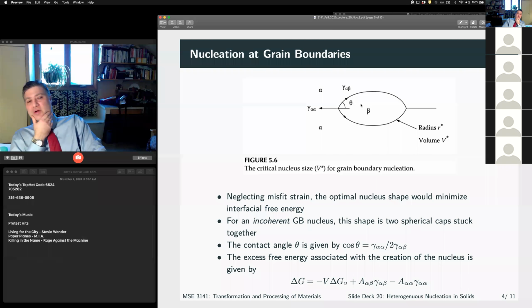And so it's the same situation that we had for solidification, except now instead of one spherical cap, we have a spherical cap on each side with an angle theta, and they're glued together, and this gives us this oblate ellipsoidal type shape, right? And so if we neglect misfit strain for a little bit, and we assume that this is an incoherent interface, and this grain boundary is also a general high angle grain boundary, and thus an incoherent internal interface, we are going to have a shape that's essentially just like this. It looks like an M&M,